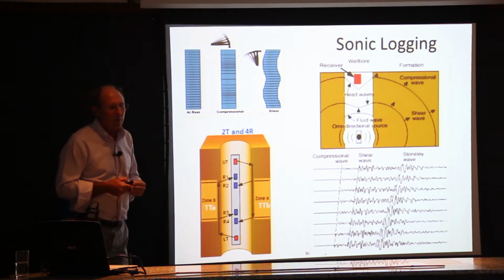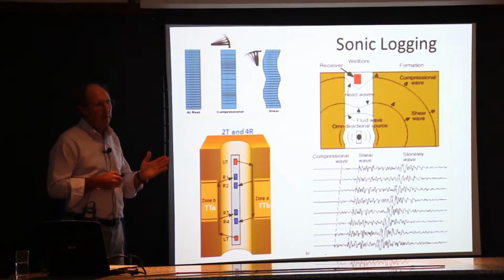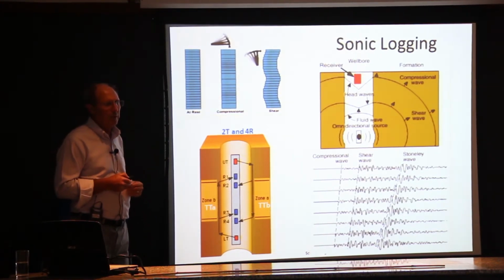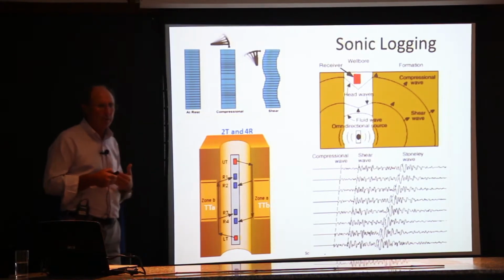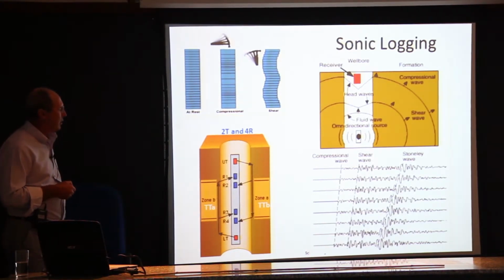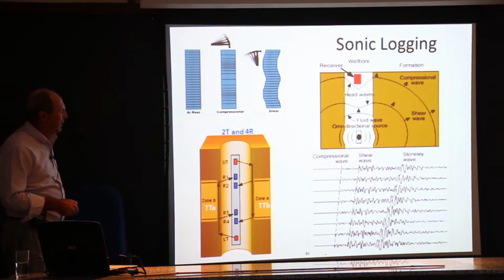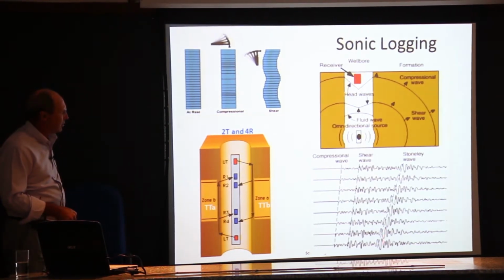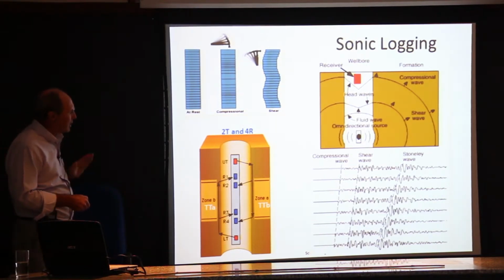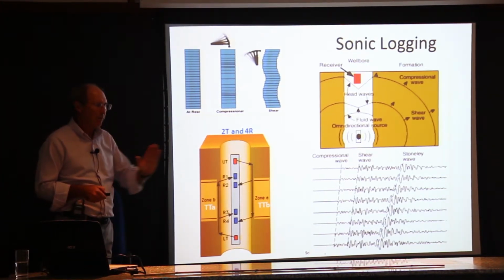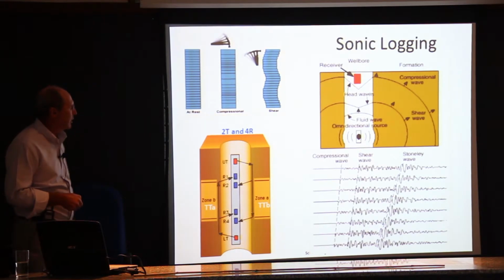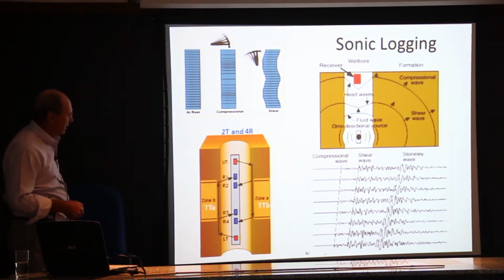Not all pre-salt wells are fractured. Maybe 1 in 10, 2 in 10 have significant fractures. But when they do have fractures, it can have a big impact on the productivity. And then the third mode that we look at is the Stoneley wave, which comes later in time. And that's the wave that I mentioned earlier would also create an electrokinetic effect, because it's actually moving the fluid in and out of the formation as it moves up the wellbore.